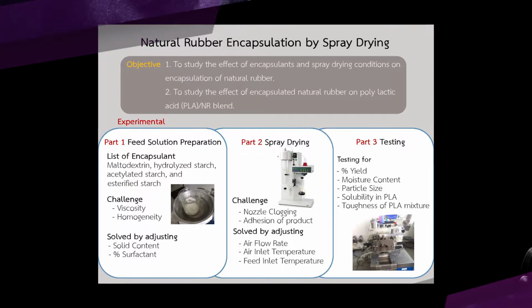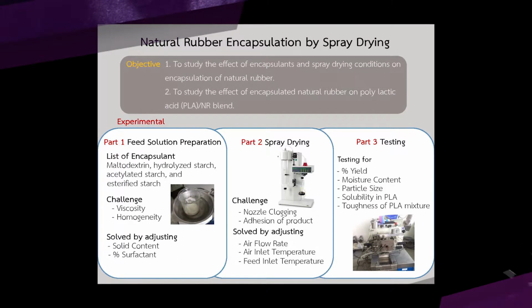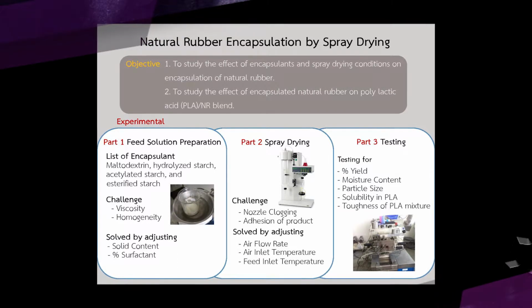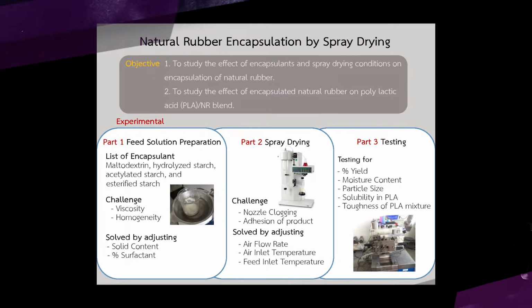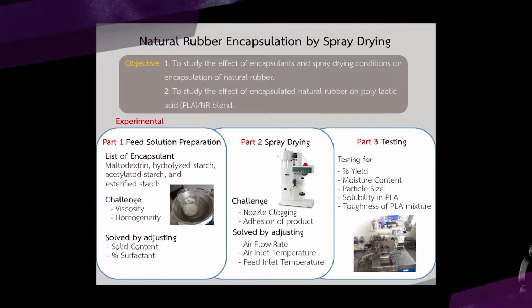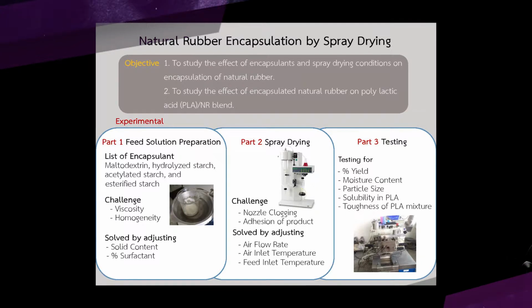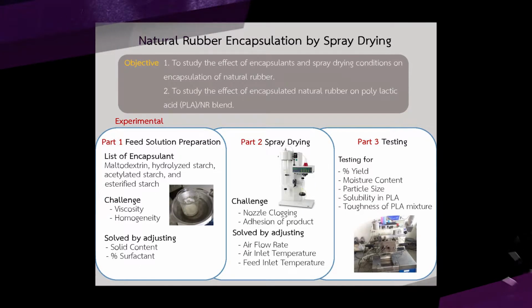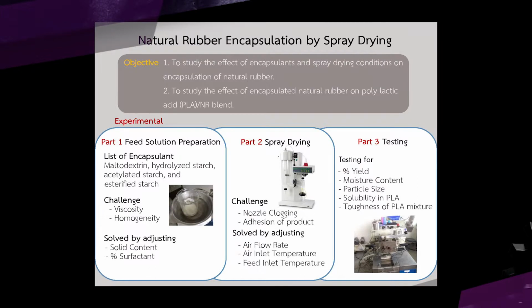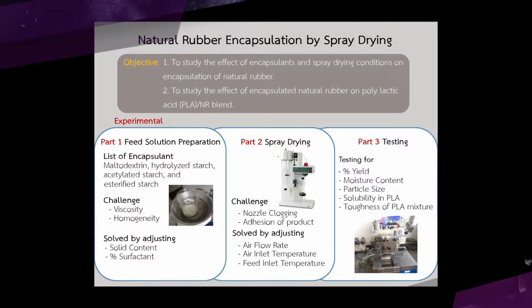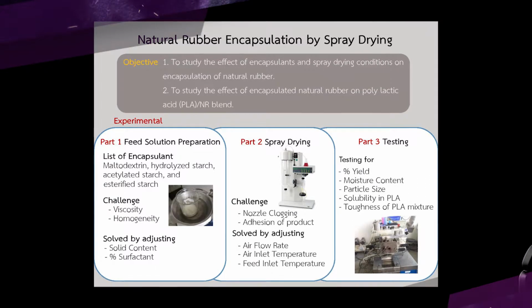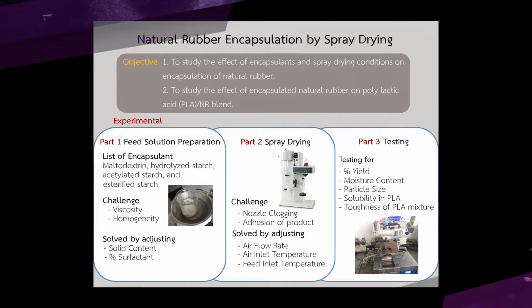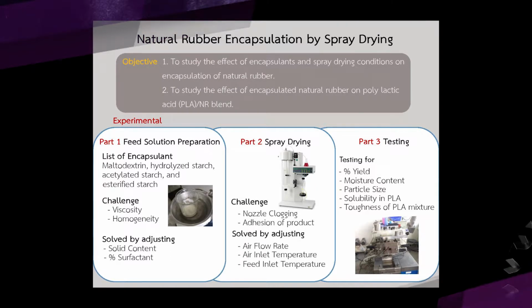Our experiment can be separated into 3 parts. First, feed solution preparation. This part will mix natural rubber with encapsulant and dilute it with water. If the solution is too viscous, we have to decrease the solid content. And if the solution is not homogeneous, we have to add surfactant into it. The second part is spray drying. In this part, the solution will be turned into powder.